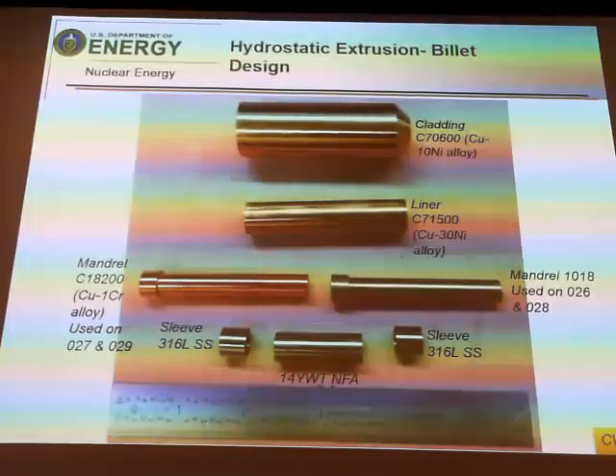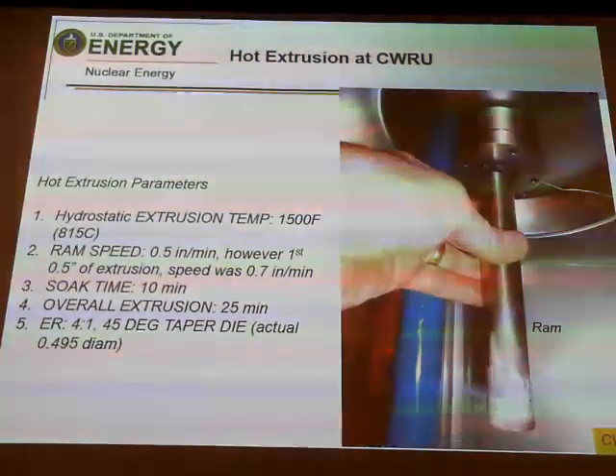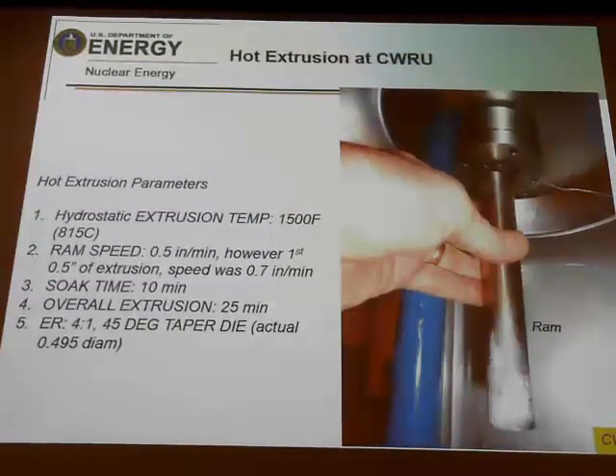All that's put together to get your hydrostatic stresses so that you can hydrostatically extrude that material. Then in one pass, you can hydrostatically extrude it at 815 degrees C in one run at a 4:1 extrusion ratio. And then you can end up with a material much longer and thin walled that you could do some testing on. So it's possibly a way to get to final tubing, but it's a pretty drawn out process.